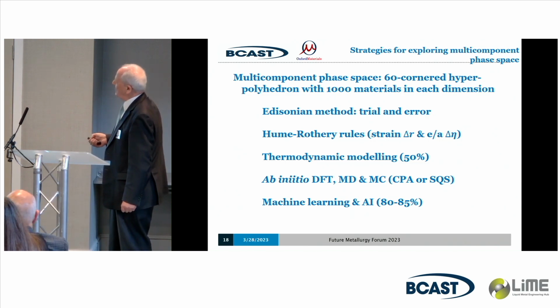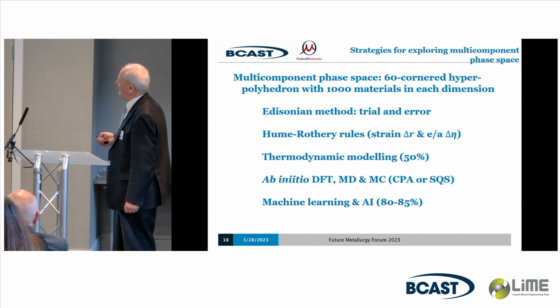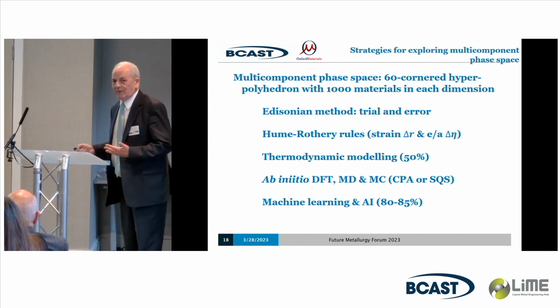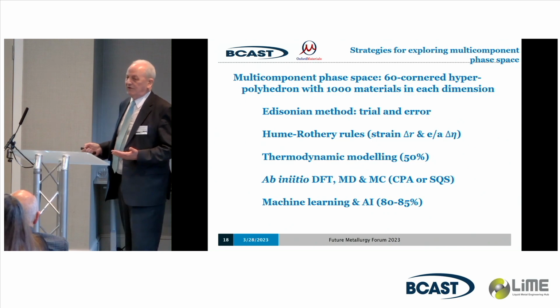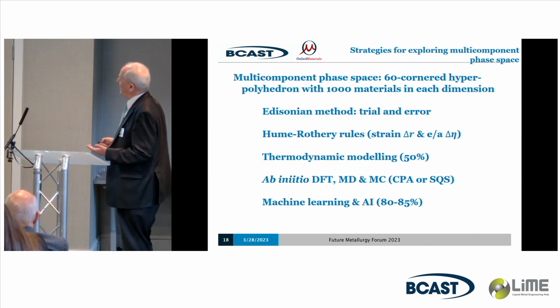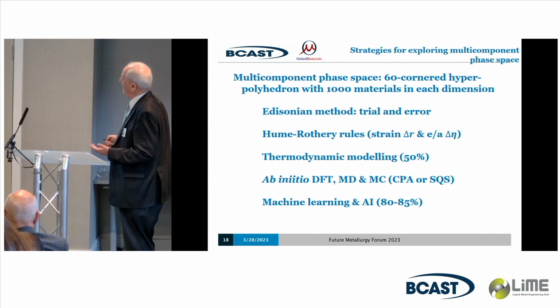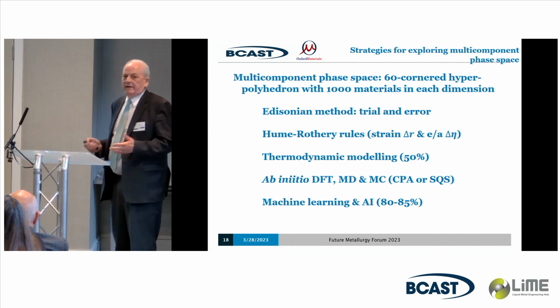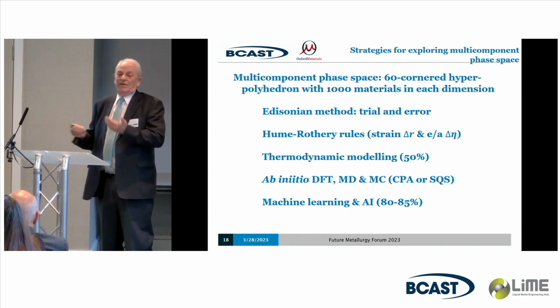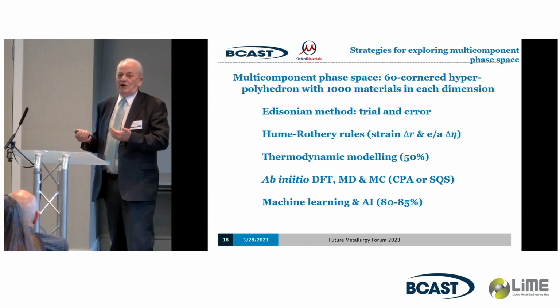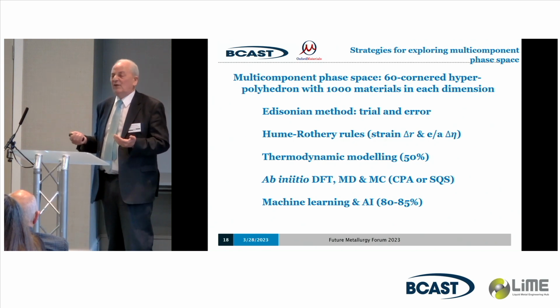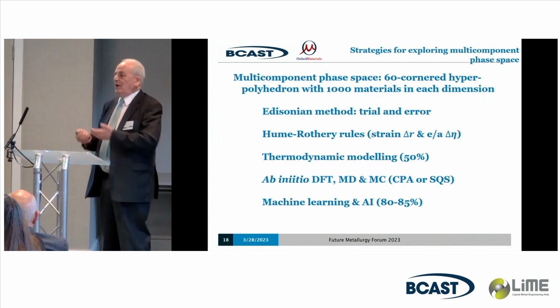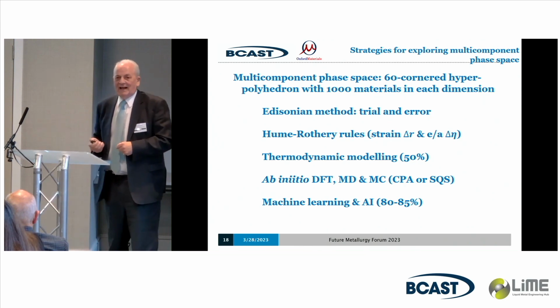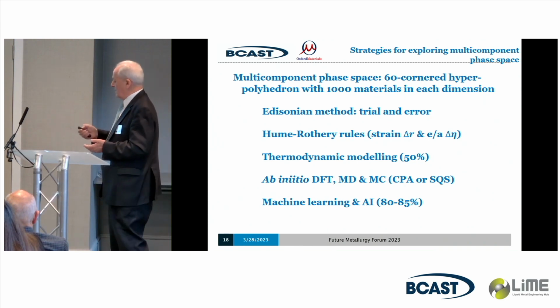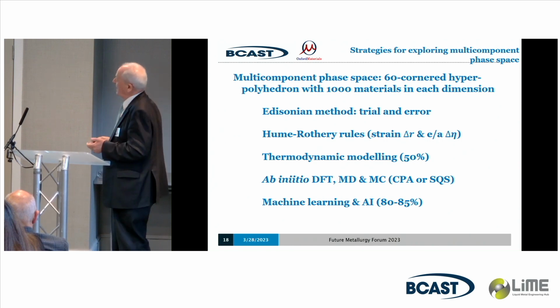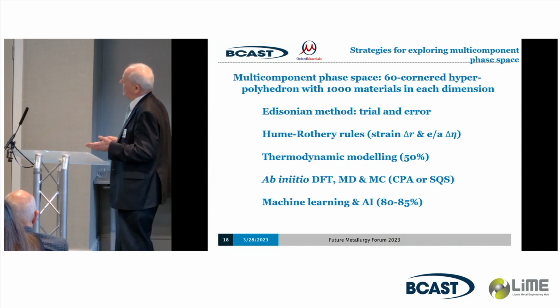So, people have tried to use extended Hume-Rothery rules. It turns out that it doesn't work. It does work, but it doesn't work any better than it works in binary and ternary systems. Basically, there are 2 effects, mechanical strain and an electronic strain. And those 2 give you a rough decision about whether things will dissolve in each other or not, but not much more than that. It works sometimes, it doesn't work other times. People have constructed multiple parameters, and it doesn't do much better.